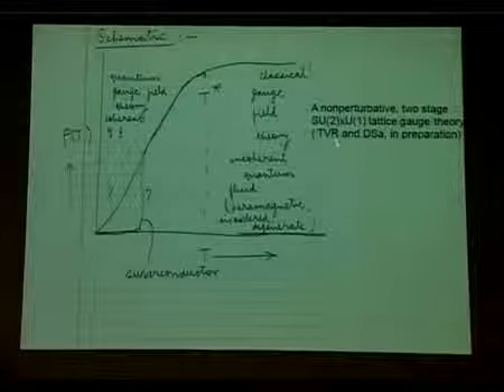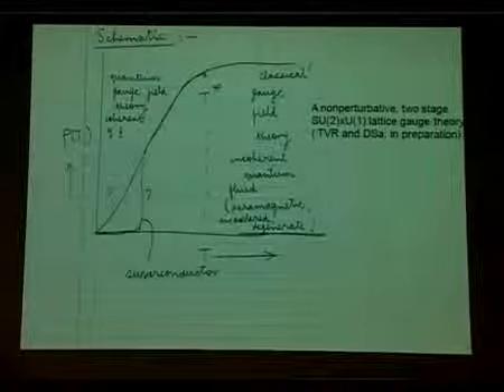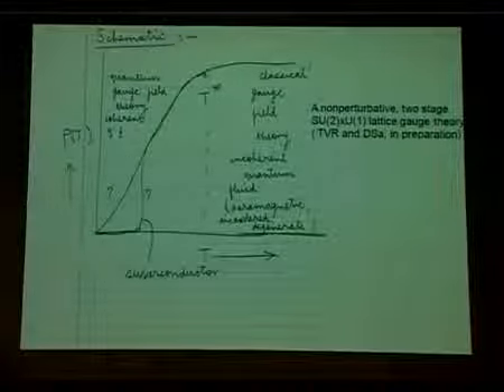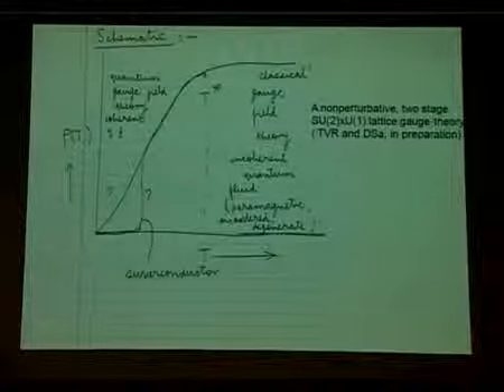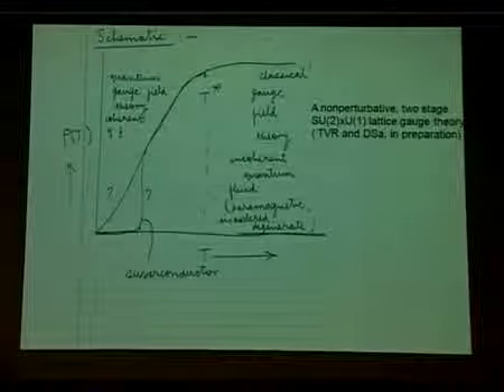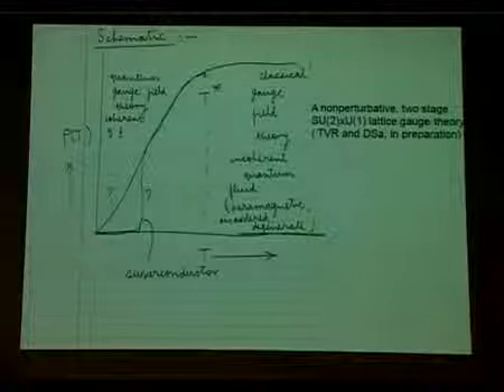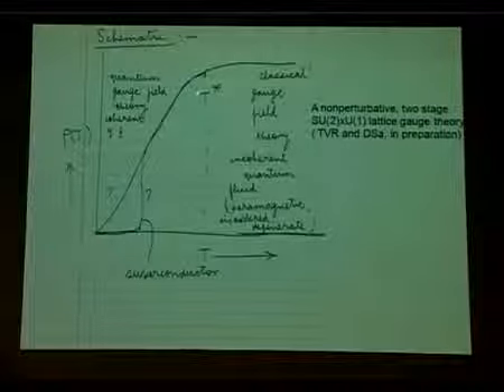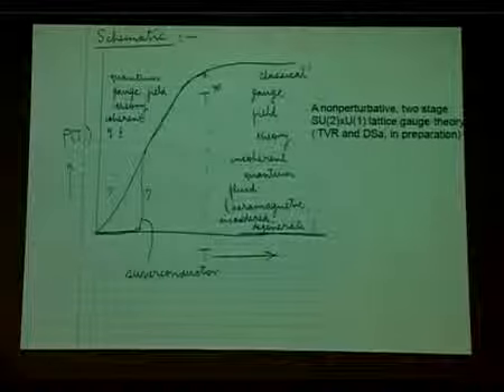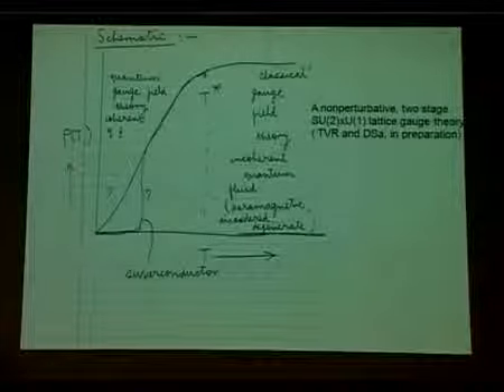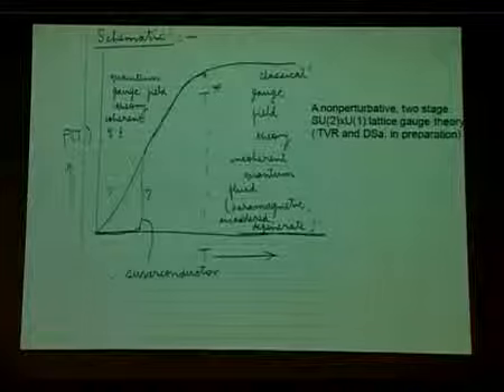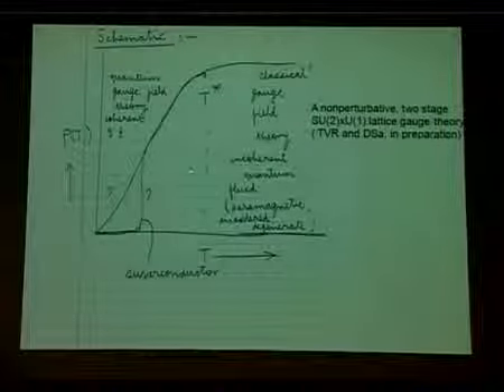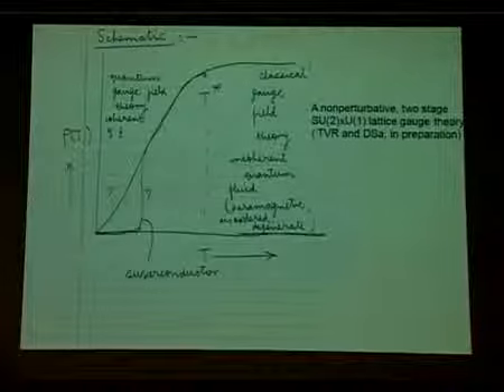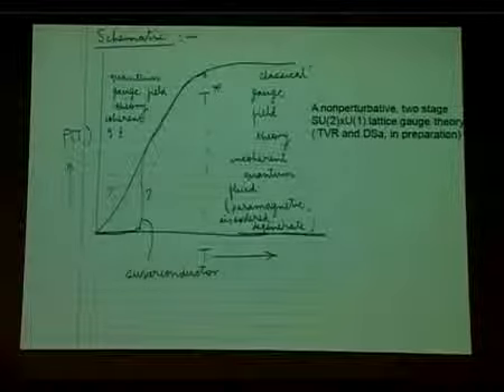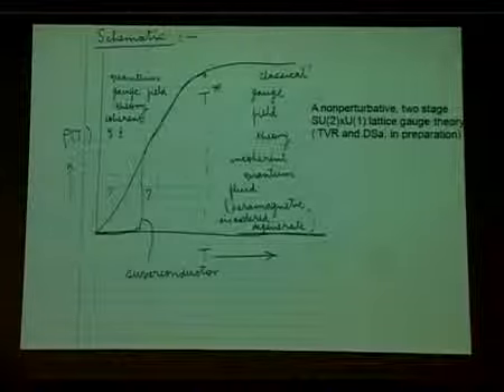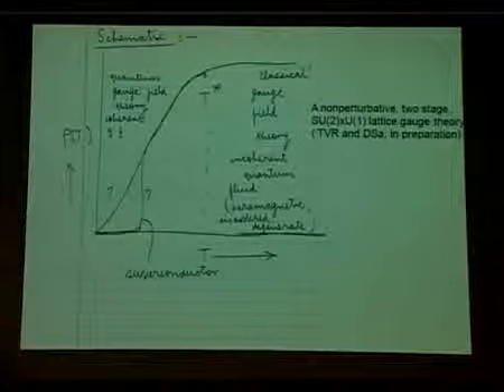We have some SU(2) cross U(1) lattice gauge theory. If you have it in the classical limit, it gives you this incoherent Fermi liquid, and then it crosses over smoothly into this coherent regime due to quantum fluctuations, and this occurs at a temperature T star, which can be shown in some cases to be rather low. And when quantum fluctuations are dominant, then it can even become a superconductor and so on. So all the differences reside here, and the commonality resides there in the coherent systems, in strongly correlated systems, and the crossover takes place at an unusually low temperature.